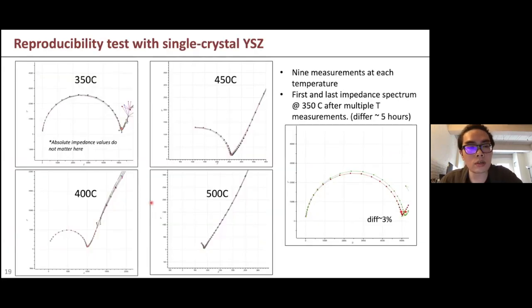So this is just a reproducibility test that I want to show, because the whole thing is still ongoing. I'm not going to show the results under strain, because of the pandemic I had to pause it, and that part of the data is still ongoing. But here I have the reproducibility test with a single crystal YSZ, and the absolute value of impedance here doesn't really matter, because I just want to show that if I operate the device under the same condition, I get the same signal.